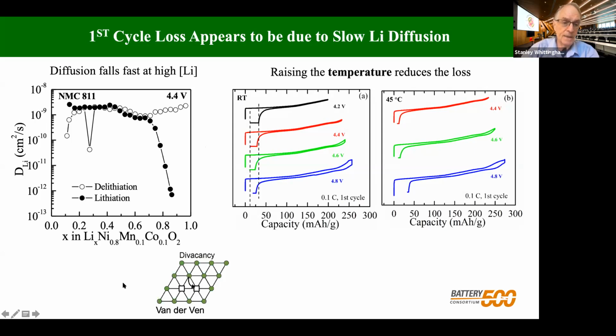And Anton van der Ven at Santa Barbara has argued that this is due to the diffusion mechanism. In this material, the lithium ions jump from one octahedral site to the next octahedral site, but they have to go through this middle site, which is a tetrahedral site. To make that jump, they want this other octahedral site to be vacant. So you've got to have this divacancy mechanism. And clearly the number of divacancies falls off rapidly as the lithium content increases. Taking the lithium out, there's very little change in the diffusion coefficient. So fast charging of this material, there's no issues at all.